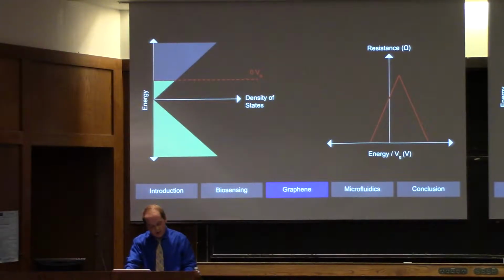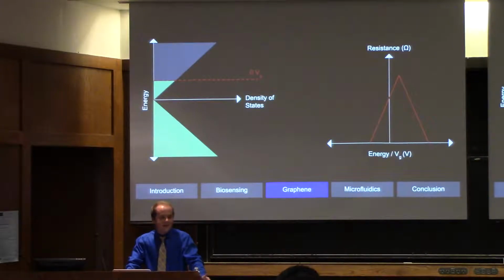When we add the biomolecules to the graphene, however, they actually transfer their own individual charge to the surface. What this does to the band structure is it fills up some of the states, as you can see here. And the graph of the resistance versus energy also reflects that. You can see how the peak of that graph is actually shifted.